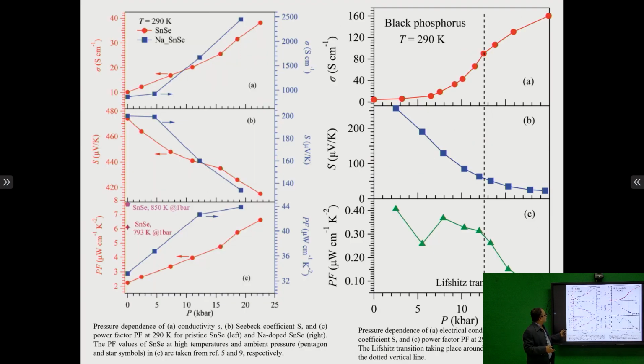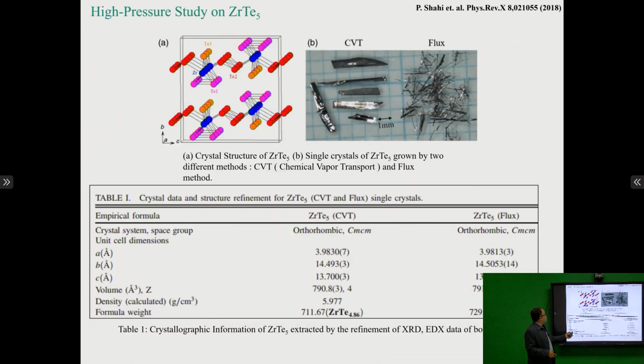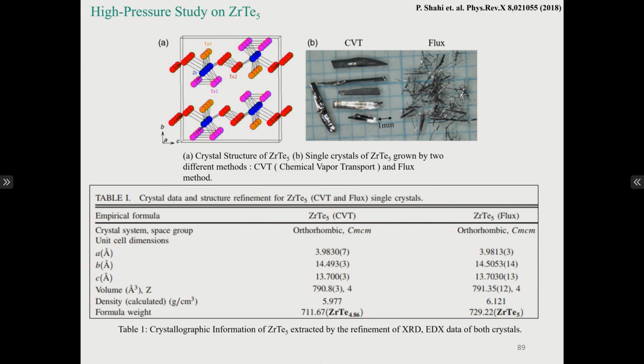We have also measured black phosphorus, which is isostructural with this one, and we found that it's not giving the same type of result as in SnSe. It means it's not common that you apply pressure and get good results. Now this is ZrTe5. This type of crystal we have grown in our lab. There are 2 types of crystals. One is grown by CVT. The flux method is also nearly the same.